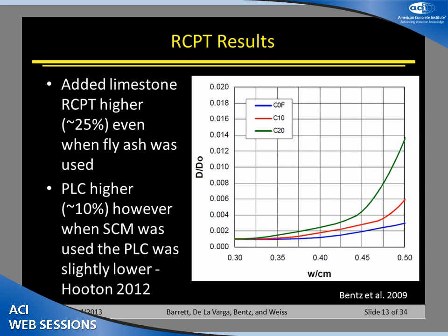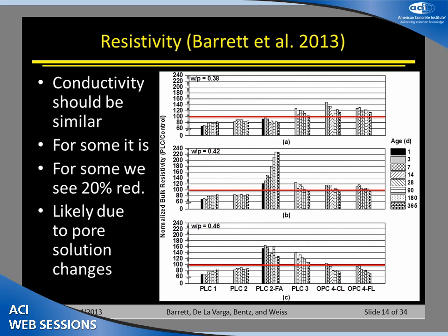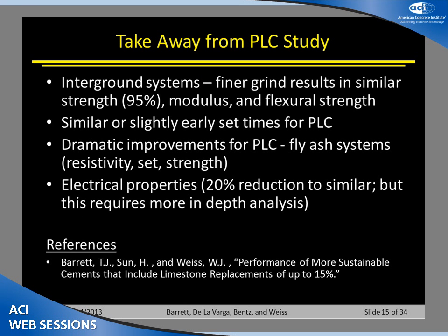Transport properties, if we're just counting on dilution, we see a little bit of an increase, but again, for most of the systems, we see a behavior in electrical properties that's relatively equivalent. We see a slight decrease down here, and we think that this is due to a pore solution change with the electrical properties, and that's something that we're still looking at because the chloride ingress numbers are very, very similar.